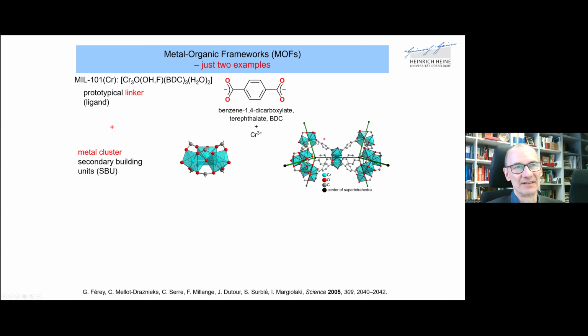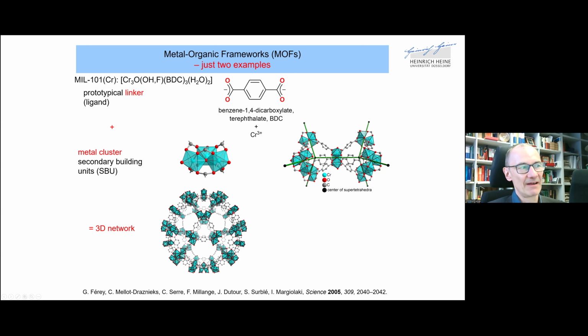In this case, it's a supertetrahedron, and the trinuclear clusters lie at the vertices of these supertetrahedra. And then two of these supertetrahedra are shown here joined at a common vertex. So from this, the whole porous network is then constructed, and shown here below is one of these pores which are now surrounded or constructed from these trinuclear clusters and the linkers in between.